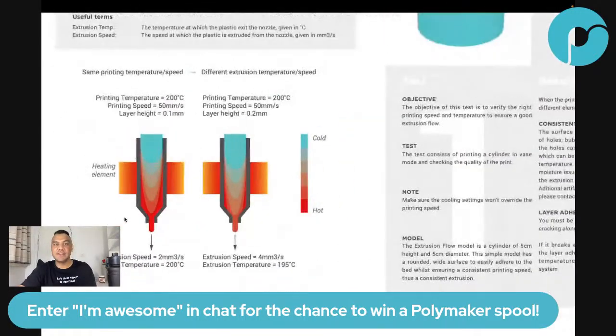You see, there is a difference between printing temperature, which is defined as the heat block temperature, and the extrusion temperature, which is defined by the temperature of the filament coming out of the nozzle. And this is very important. And I wish people would use that vocabulary. Why? Because sometimes to solve something, you have to increase the extrusion temperature. And yes, increasing the printing temperature can help, but there's many other things that can help. For example, lowering the speed. Lowering the speed will also increase the extrusion temperature. So there's a big difference between these two. And this is what he's saying. And I really like that he said that, because it's very important. And not a lot of people do that.